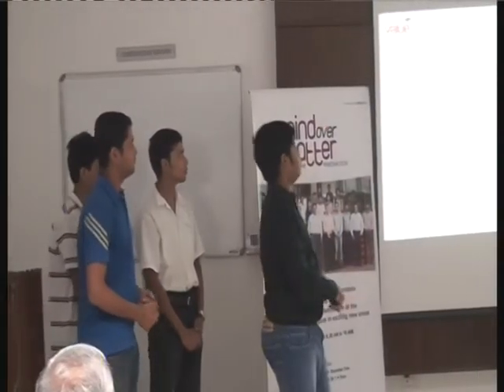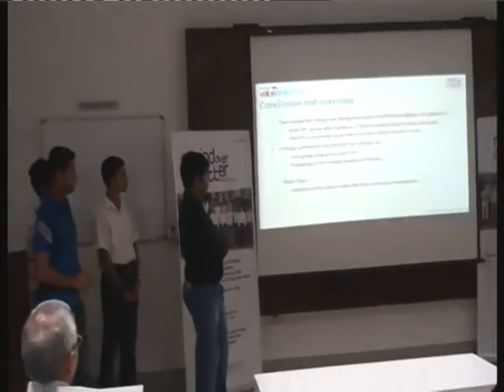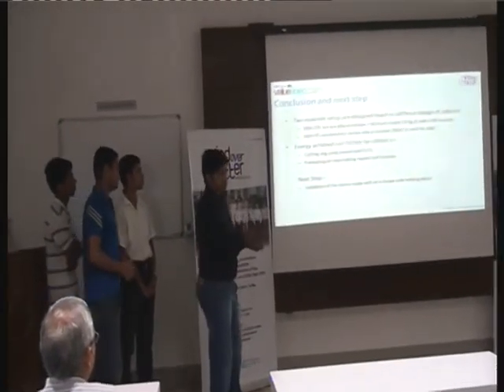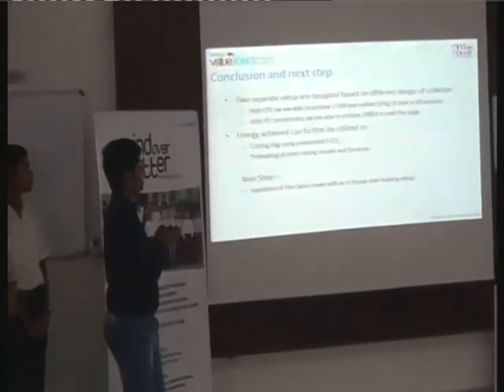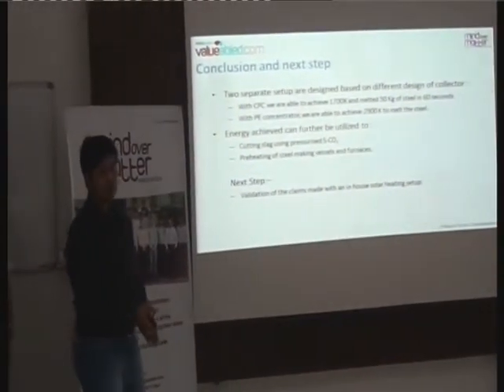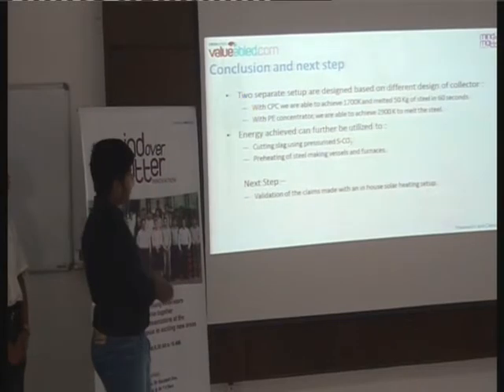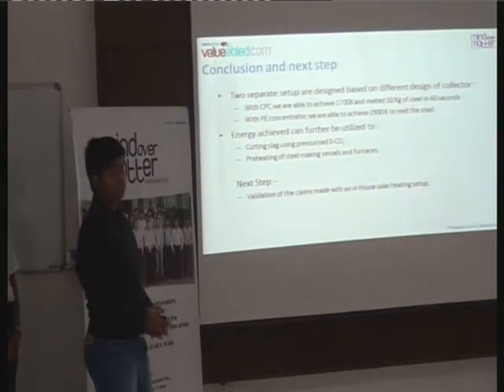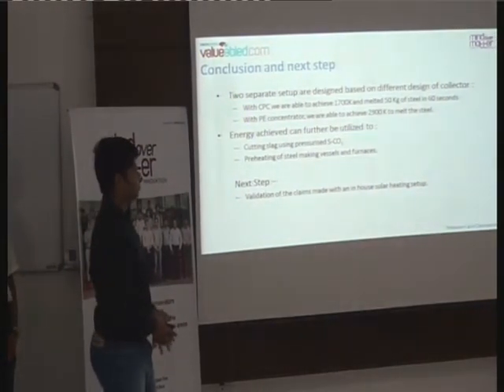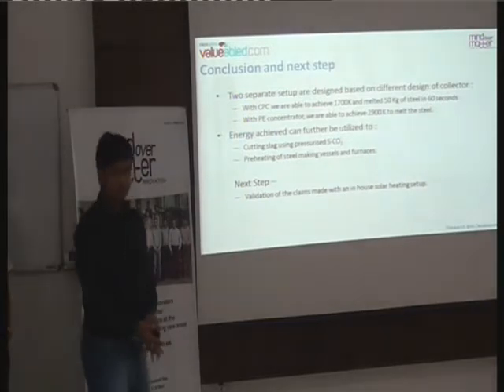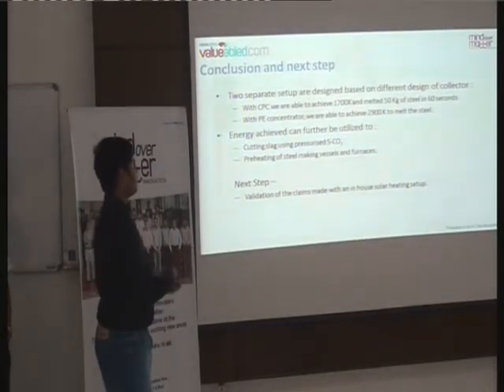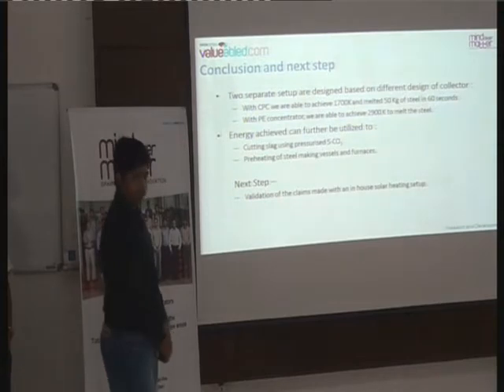Coming to the conclusion, till now we have seen that we are able to make two separate setups. One uses a CPC, a compound parabolic concentrator, to achieve 1700 Kelvin and melt 50 kilos of steel in 60 seconds, and the other is the parabolic ellipse concentrator, which achieves 2900 Kelvin to melt the steel. And the energy from the two setups can be further utilized for cutting of slag and preheating of the steel.